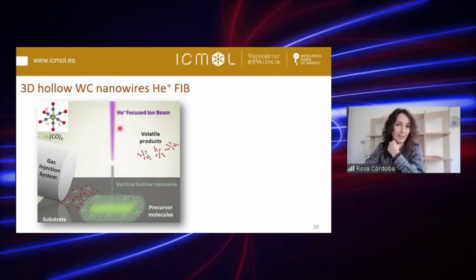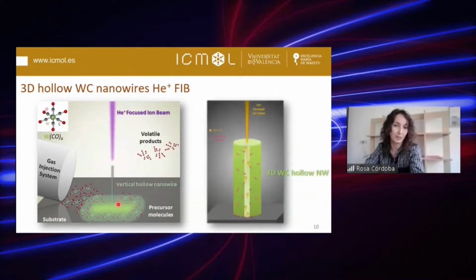So in this specific case, how can I create these hollow vertical nanowires? The beam stays at the same position for the deposition time, producing two effects. The first one is the decomposition of the precursor molecules absorbed in the substrate and in the growing material, and at the same time, the beam is creating a cavity, a hole at the center of the wire, mainly due to the helium focused ion beam milling.